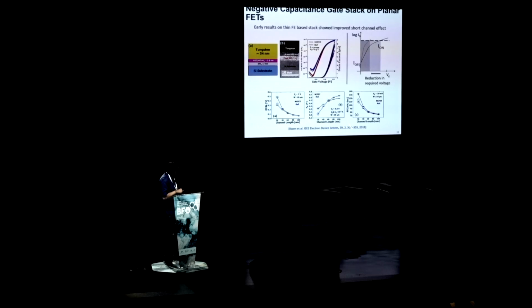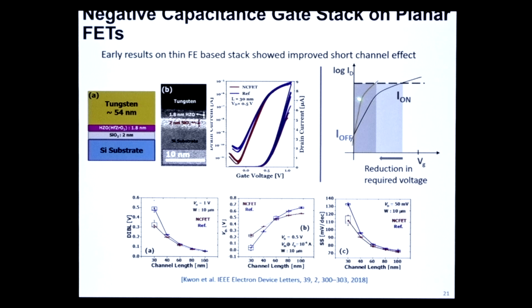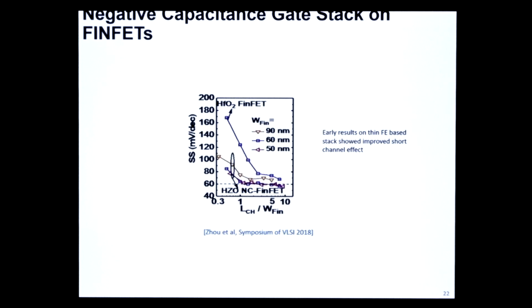So, this is back in 2018, we started making transistors because this hafnium zirconium oxide is compatible with silicon, so we could immediately go and start making transistors. And we started seeing what we projected. If you remember a few minutes ago, I said that a negative capacitance effect is supposed to steepen the curve like this, the IV curve, and that's what we started seeing in the actual transistors. These were planar transistors. We also then went to FinFETs, and I'm not going into the details of it, but basically we saw the effects that will come for capacitance enhancement in FinFETs as well.